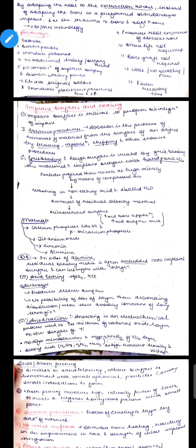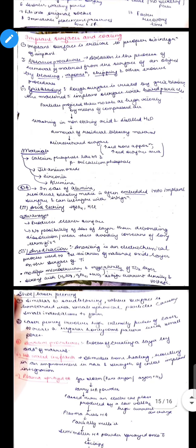In this, a rough surface is created by grit blasting the machined titanium implant surface with hard particles. The particles are projected through a nozzle with high velocity by means of compressed air. Then washing is done in a non-etching acid and distilled water. Then the residual blasting material is removed, which leads to a micro-textured surface which increases the bone apposition and also increases the surface area. The materials used for grit blasting are tricalcium phosphate, titanium oxide, zirconia, and alumina. However, with alumina there is a problem because the residual blasting materials remain embedded in the implant structure and interfere with the integration.